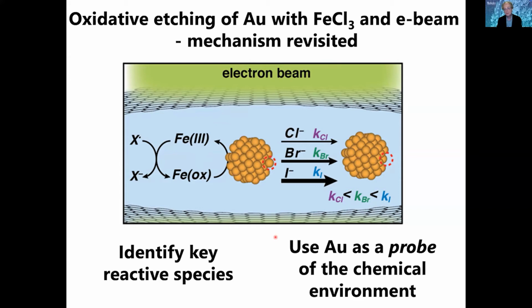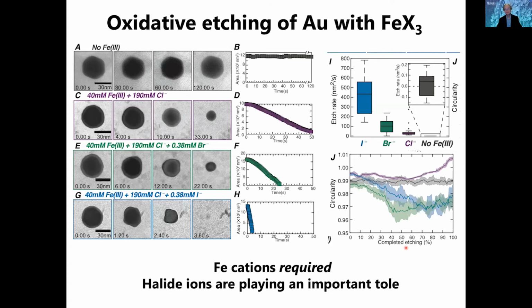And in fact, almost in a sense, we're starting in these works now to invert this and to say gold itself serves as a probe of the chemical environment inside the liquid cell. We can make variations inside there, and what happens to the gold can become a kind of diagnostic for what's inside the liquid cell. So here you can see a few experiments that have been done recently by Michelle Crook. And what you can see here is a case where if we have no iron chloride present, there's absolutely no etching of the nanoparticle. So it's a little bit like what I showed you before.